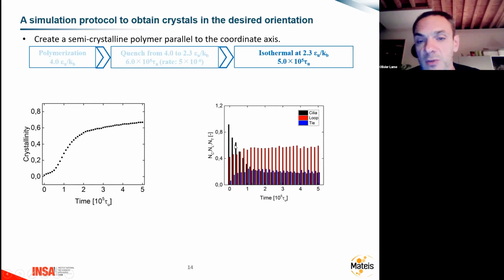For example, here, the decrease as before of cilia, the increase of tie molecules, the increase of loops. So with this statistics, we want to analyze deeply all that is happening to the amorphous phase during crystallization and after, during a tensile test, and try to understand the origin of the mechanical properties from the topology of the amorphous phase.